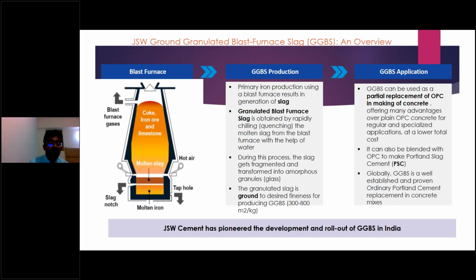When it's heated up to 1500 degrees centigrade, as shown in the diagram, the heavy metal separates, that is iron. We take it out and go for steel production of various items. So for each ton of the raw mix, we get 700 kg steel and 300 kg molten slag. That molten slag has to be properly treated and quenched into fine granules using technology. If you just allow it to flow, it becomes solid rock and we cannot do anything. So using the latest technology, we make it into small granules like sugar. This is called slag, or blast furnace slag.